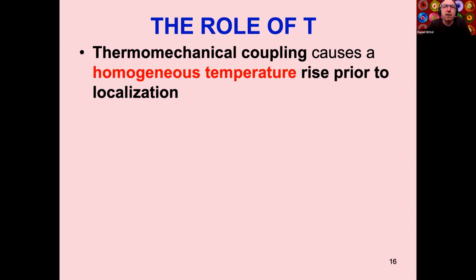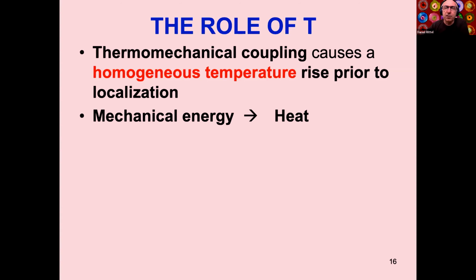So we'll start by stating the obvious, that thermomechanical coupling causes a homogeneous temperature rise prior to localization. And here I want to emphasize that I'm talking about what brings about localization, and not what happens once you have the localization. Indeed, from a spectacular point of view, the post-localization failure is very dramatic, with temperatures in the range of several hundred degrees inside the band. But the question that you as an engineer would like to ask is, how does the story start? Why does it start? Can we prevent it? Do we have a criterion for it? So as long as deformation is homogeneous, then you have a homogeneous temperature rise in your solid. And then you can say that the mechanical energy is transferred into heat.